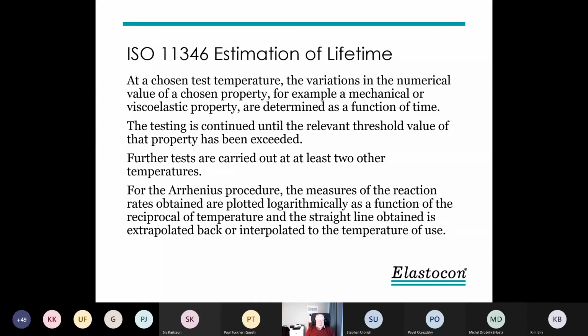And the testing is continued until we have reached what we consider to be end of life or something like that. That's always the difficult thing, to know what is end of life. When it doesn't function anymore. If you don't know that, 50% reduction is normally used. And then 2 more tests are done at other temperatures. And then we can do a so-called Arrhenius plot.